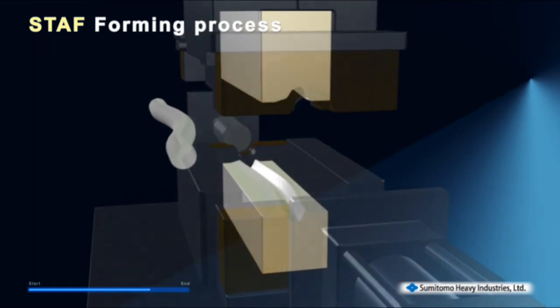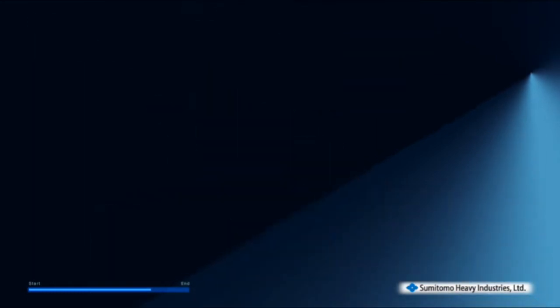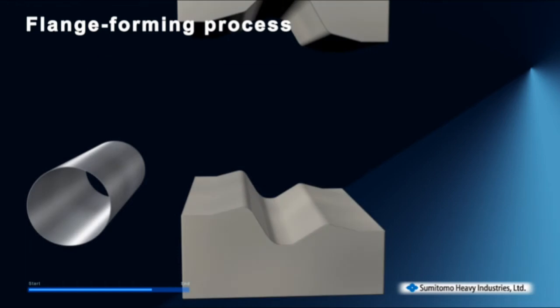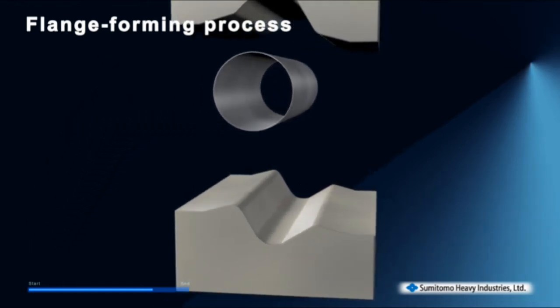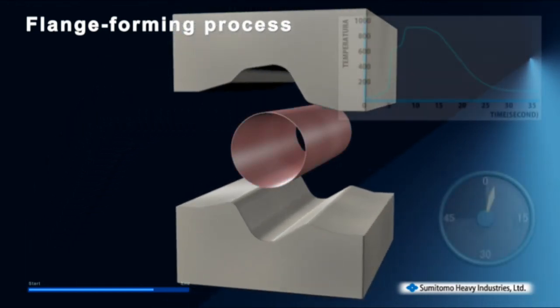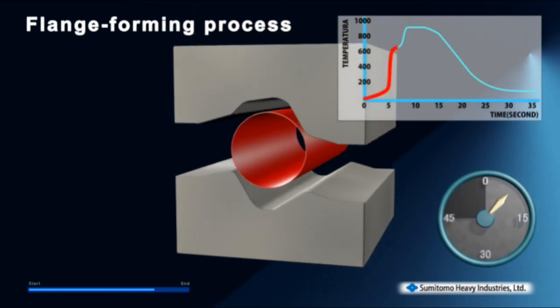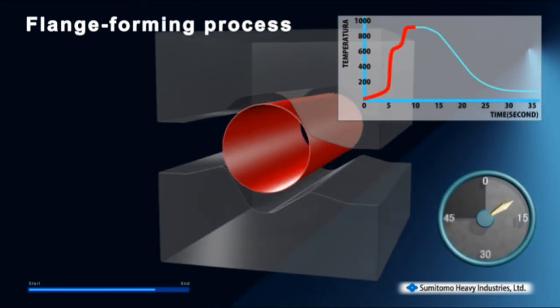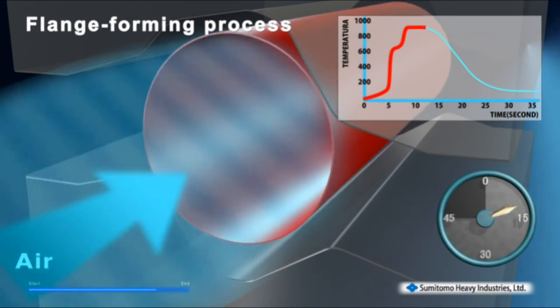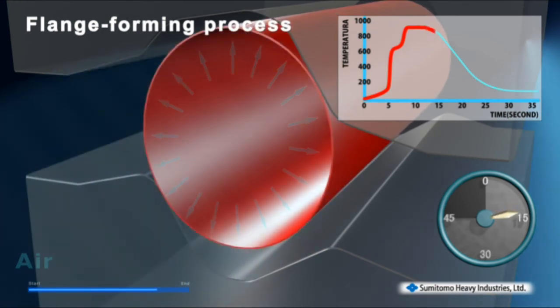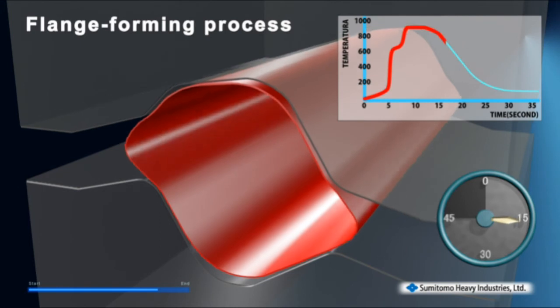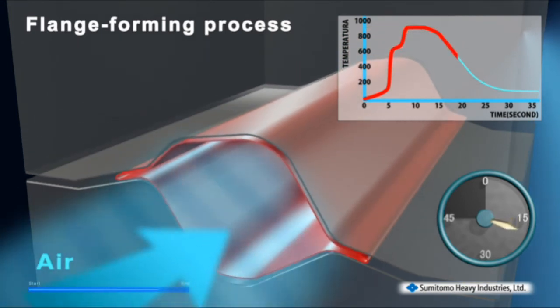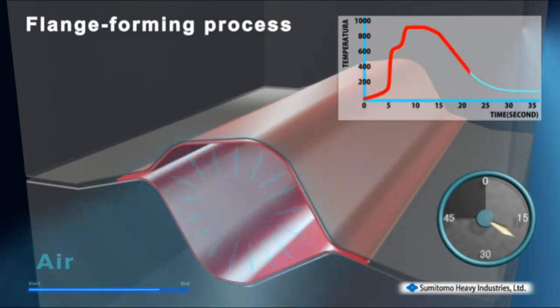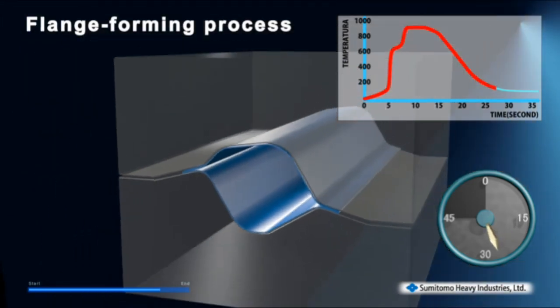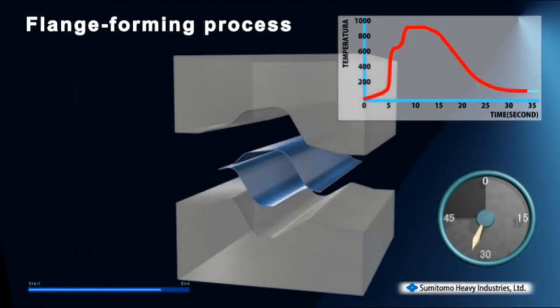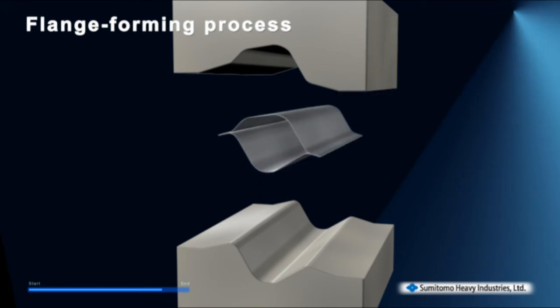Take a look at a cross-section. We set the pipe and heat it at 900 degrees for 10 seconds. The die is half open when we supply high-pressure air and inflate the flange sections. At the same time, we close the die to shape the pipe. Then, in order to properly quench the corner radius sections, we again supply high-pressure air to press the pipe against the die while simultaneously quenching. We remove the piece after cooling for 20 seconds.